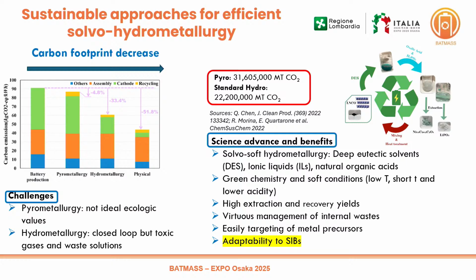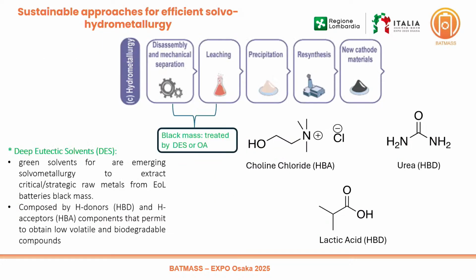But there is an opportunity. The opportunity of the last years is to study new types of solvents, maybe organic solvents that are cheaper and also have a much lower environmental impact. One of the most talked about and most studied solvents in the last few years are the deep eutectic solvents. For all of you who may be new to this term, these solvents are a combination of two or more components able to chemically interact with each other through a hydrogen bond, and this interaction is able to decrease the melting point, so we can find the composition in a liquid phase. Because it's liquid, we can use it as a solvent. In some cases, it's possible to have the composition in a liquid phase even at room temperature. Different studies show really good efficiency in terms of application. And in the case where we have an organic acid, it can be used as a leaching agent.